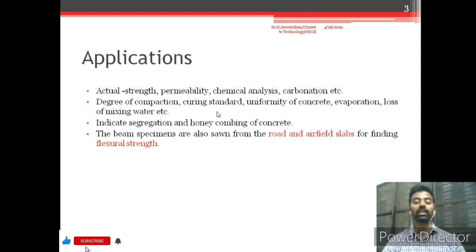And curing standard. The conventional specimen is cured under water, so it will be 100% cured. In the actual case, the curing might not be that sufficient, so there will be a loss of strength. Generally, after conducting this test, it is found that the strength of the exact specimen versus the specimen which we take in a cubical mold has a plus or minus 15% variation due to this change.